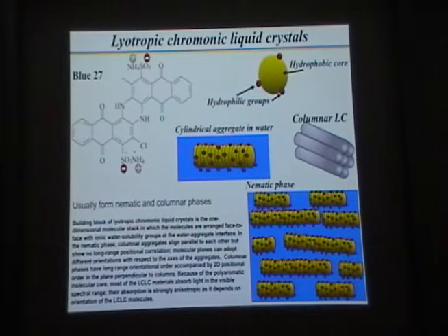And in this particular case, because you have the hydrophilic water-soluble molecules on the periphery, those charged groups over here, and an aromatic hydrophobic core inside, the molecules tend to assemble into the long stacks so that they can expose the hydrophilic parts of molecules to water, right here on the periphery of those stacks, while hiding the hydrophobic parts of the molecule from water, right?